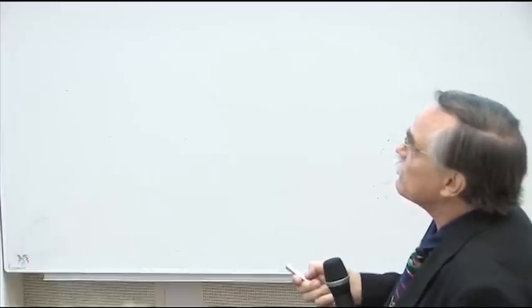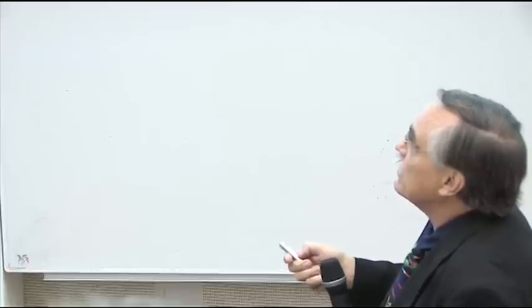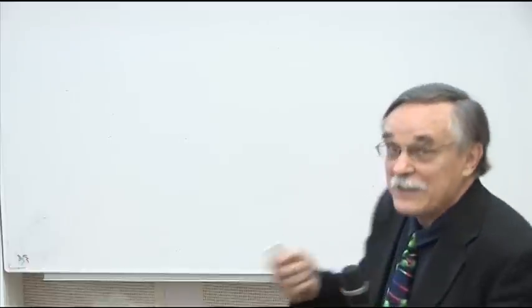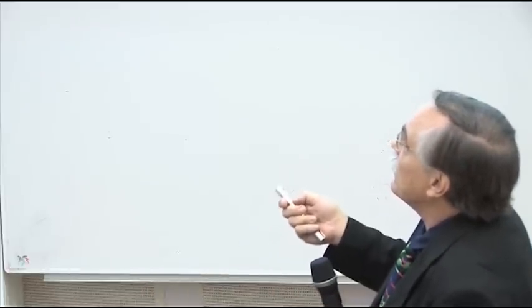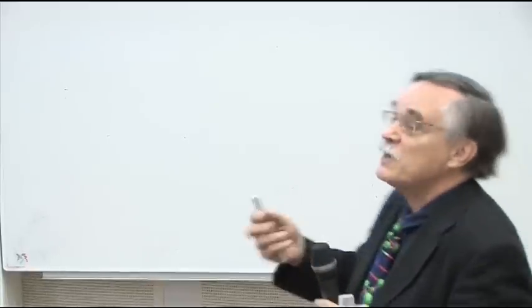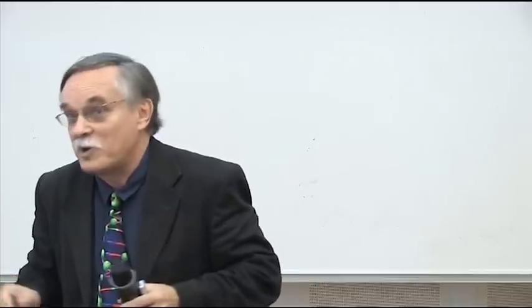Here you can see the non-magnetic calculations at room temperature don't quite agree. The experiment are the white dots. The theory are the red. He's just plotting intensity here from the calculations. If he does it with the magnetism, you get the splitting and, in fact, a much better agreement. So it means that the magnetism is still present even above the Néel point where you get paramagnetism. The magnetic influence on the iron is still present and influencing the phonons. Okay.